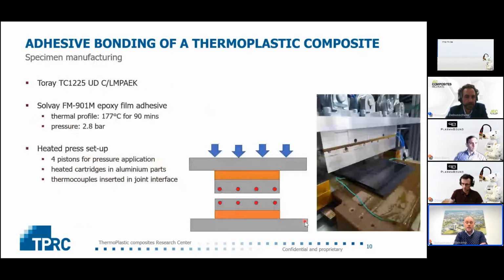We then prepared TC1225 unidirectional carbon low melting PAEK laminates provided by Toray. We used an epoxy film adhesive supplied by Solvay, the FM-901M, and we cured that to the thermoplastic laminate using a heated press, which is piston operated, so we can apply pressure and heat the whole assembly up to 180 degrees in this case for a 1.5 hour cure time, pressure of about 3 bars.